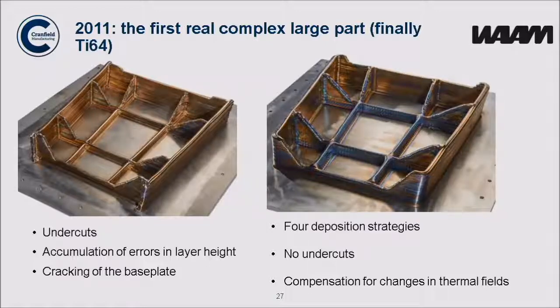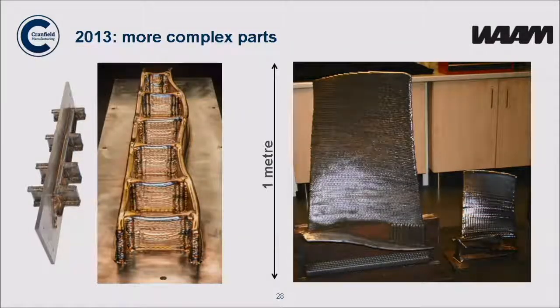So when we did the final part, you can see we have different deposition strategies. The geometry looks very different. We have no undercuts, and most importantly, we introduce compensation for changes in thermal field as you go around the part. In different areas of the part, you have different thermal mass. This changes the thermal field, so you get layer height errors, undercuts, and also defects if you don't do anything about that.